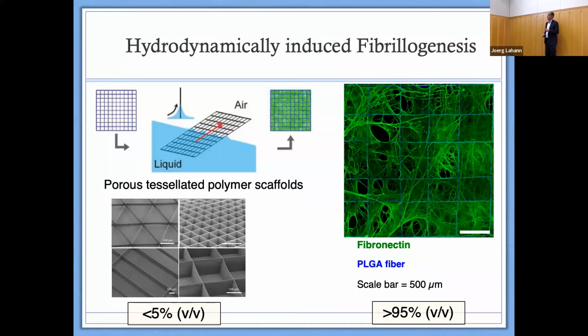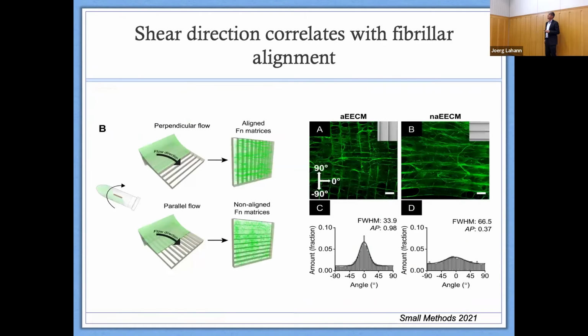Okay, so this is a stain for fibronectin. We can also confirm the presence of cryptic binding domains in those systems. So this is very much like cell-deposited fibronectin. And the nice thing is, because it's shear induced, we can control the shear field relative to our scaffolds, and we can induce directionality in those fibers. By using flow perpendicular to the main direction of our pores, we can align the fibers that we form, the ECM fibers, and we get nice alignment.